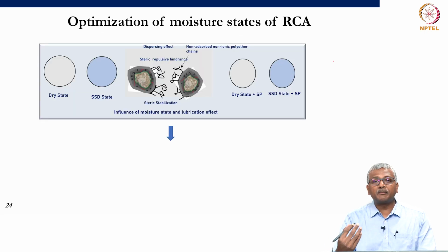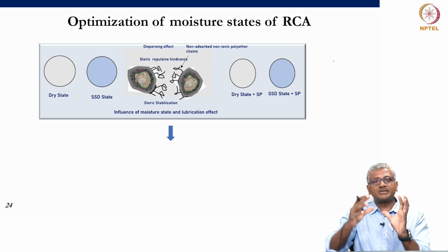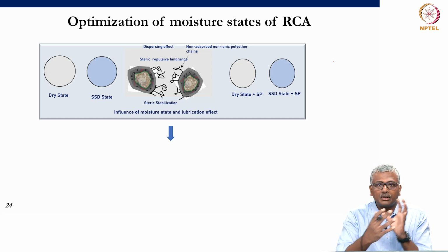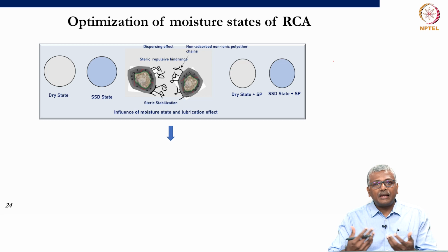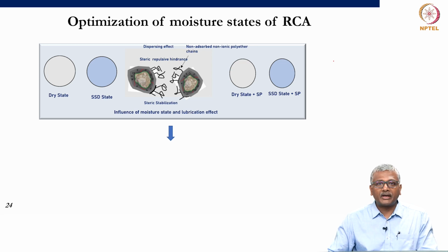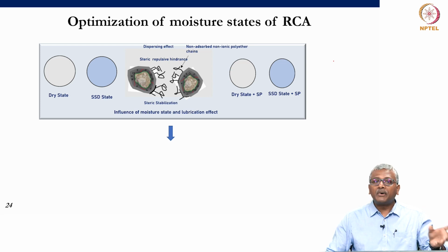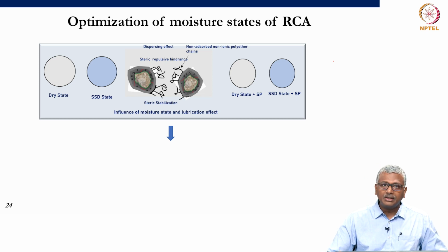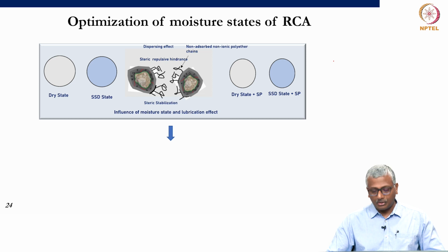Now, you can also optimize moisture states of the RCA. We know that because of the adhered mortar content, the recycled concrete aggregate may have a lot of surface moisture, and that needs to be compensated by achieving a saturated surface dry state. But when you design concrete with it with chemical admixtures like superplasticizers, which tend to then adsorb on the surface of cement particles and also aggregate particles and lead to a repulsion effect, does that help us in achieving better compaction in roller compacted concrete? We saw that packing densities could be achieved, but when you actually do the concrete mix design with the cement and chemical admixtures and water, are we able to get the same level of compaction or not?